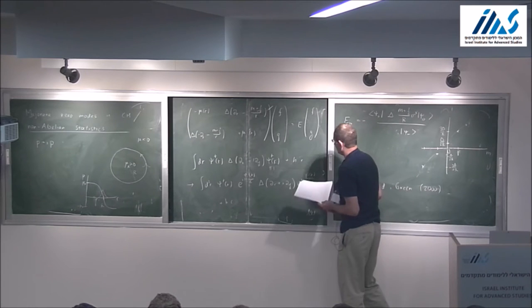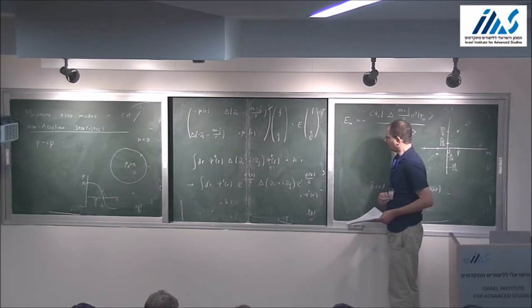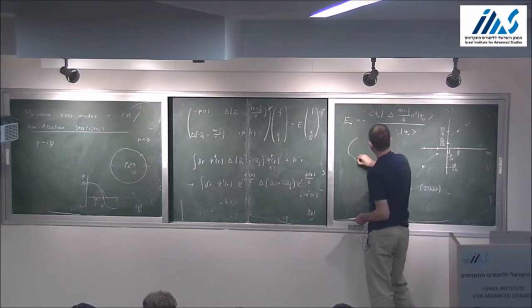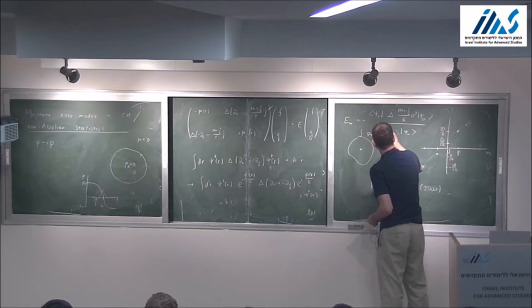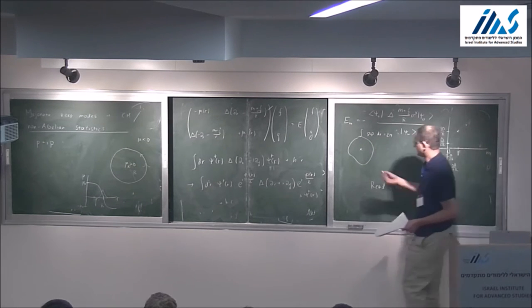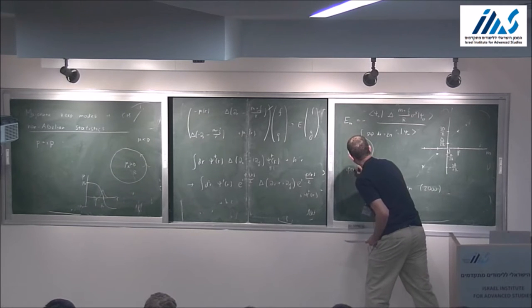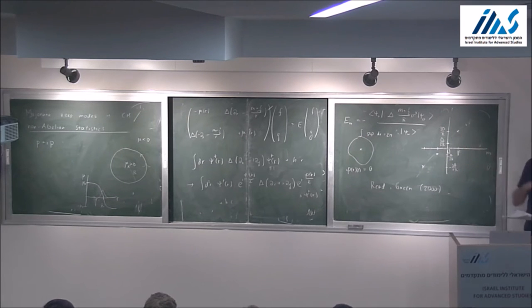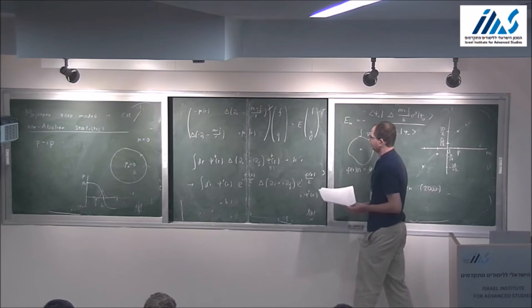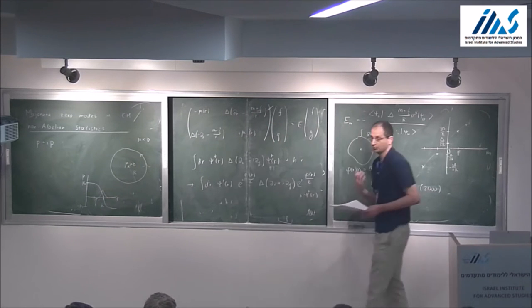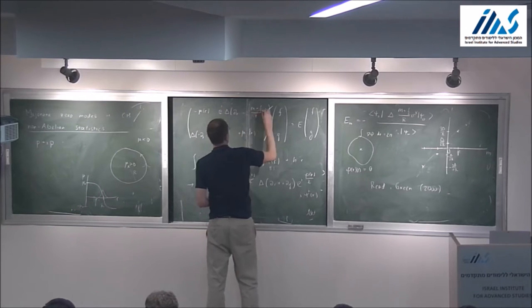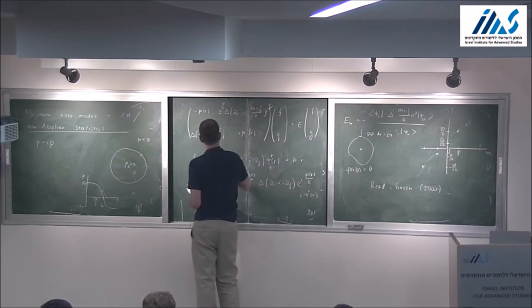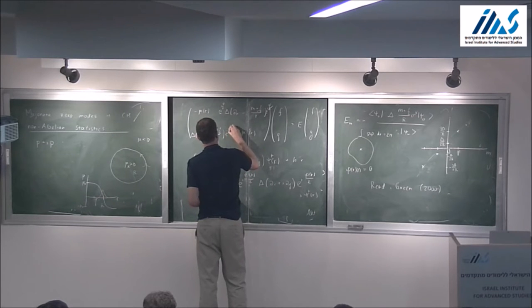So what we want to do is consider a spatial configuration of this phi which corresponds to a twist by 2 pi. If you go along any closed loop around the vortex, then the line integral over the gradient of this phase is going to be equal to 2 pi. So phi of r, theta, is equal to theta, where theta is the polar angle. The way this would modify the Bogoliubov-de Gennes equation is that you need to add to the pairing term e to the i phi over 2, which is e to the i theta over 2, and same thing here, e to the minus i theta over 2.